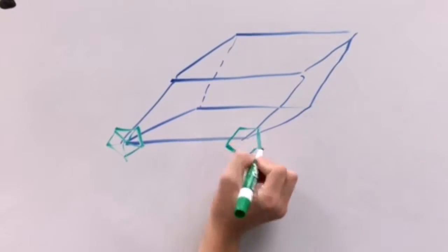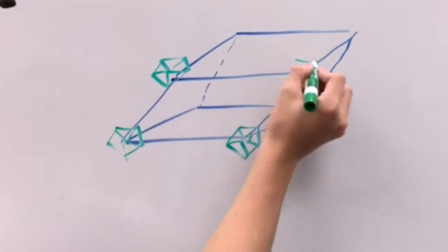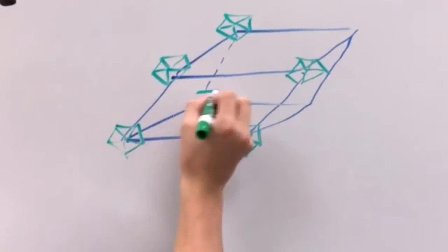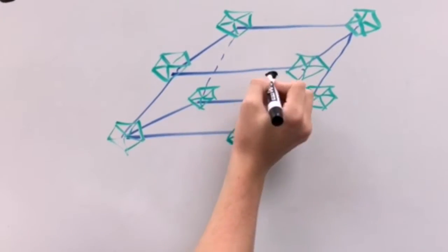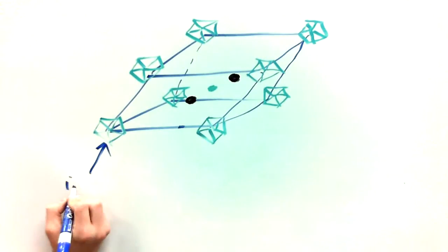It is more commonly referred to as B4C because the material is capable of forming a large variation of carbon concentration without resulting in interstitial occupancies or phase separations.